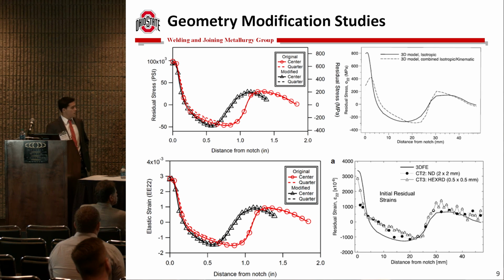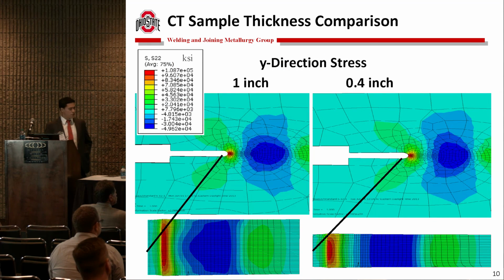And so there are actually two sets of lines here, one from the mid-thickness plane and one from the quarter-thickness plane. And since they lie pretty much on top of each other, that means the middle half of the sample has a uniform distribution of residual stress and strain. This is just an illustration of that. You can see the profile here is pretty consistent. It's not some very narrow peak in the middle.